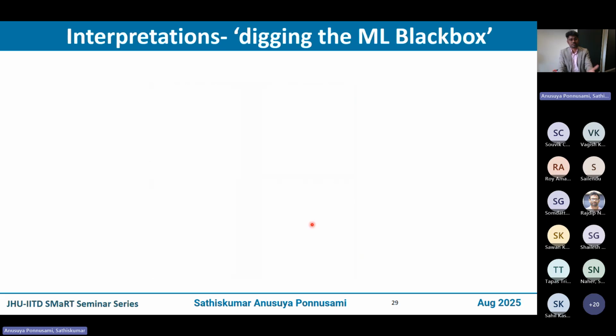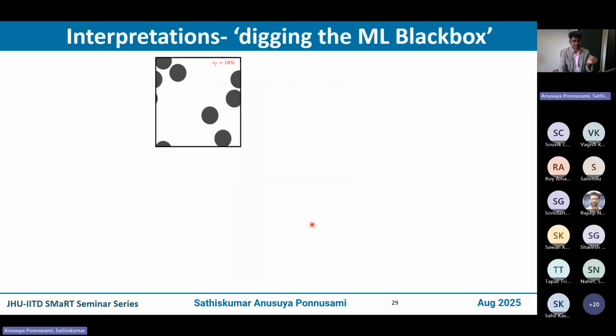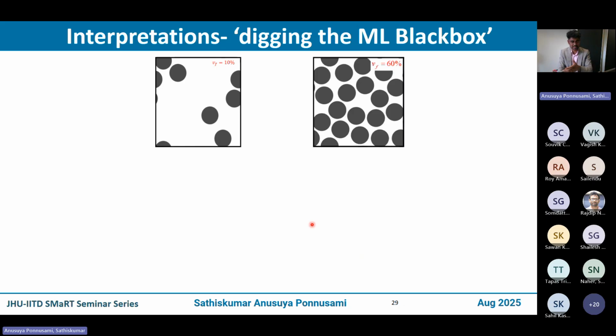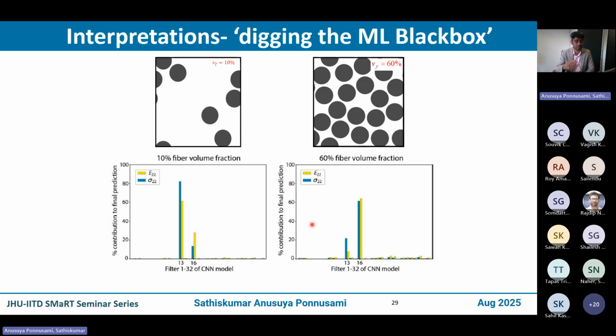But what we do, we go one step further to see how these features are considered important for the predictions. And that is where you see here we took two different samples from two different extremes of volume fractions. And what you really see is the contribution of those features. You see two main peaks. The peaks are reversed in the bottom two figures. The reason is in one case the volume fraction is high, and on the left side the volume fraction is lower. Accordingly, if you focus on this particular graph, what you see is two peaks. One corresponds to filter 13, which is the fiber phase. It identified the fiber phase completely, and the other filter identified the matrix phase, and you see those are peaked, which means the model considers these two features to be important in the predictions.